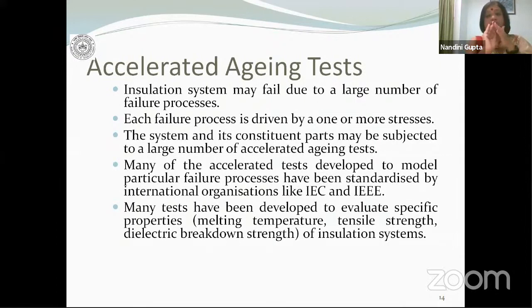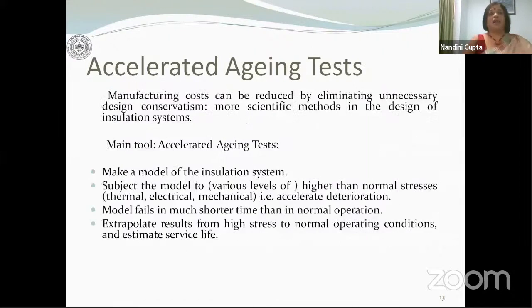Because of abrasion of the insulation, there might be a gap formation. When you have gap formation and there is an electrical field, you know what happens, partial discharges happen. And so therefore you have electrical deterioration. So you start with thermal expansion, then thermal stresses. As a consequence of thermal stresses, you have mechanical stresses. As a consequence of mechanical stresses, you have electrical stresses.